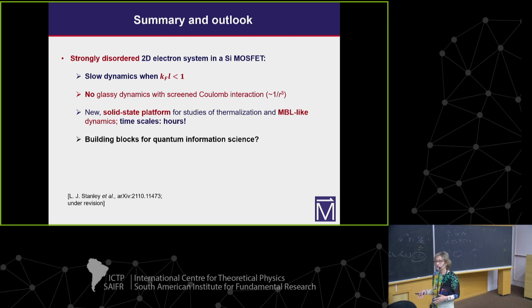Was there a difference? Yeah. With the screened Coulomb interaction, we found 2D Mott variable range hopping. And without screening, it was more like just activated behavior. But we are relatively close to the metal-insulator transition, and this is what people have been finding. So I don't know, yeah.